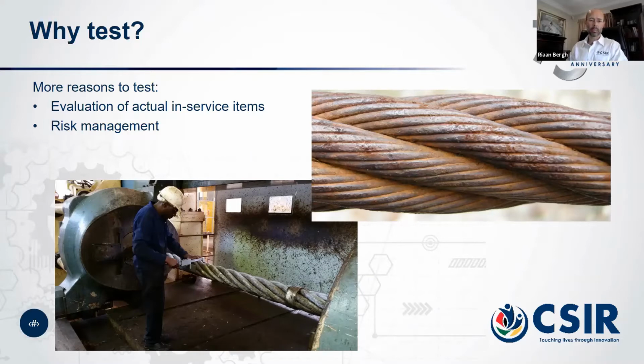But when we tested the rope to destruction, we found that it had only about 38% of its rated strength remaining. And the condition on the interior of the rope was actually quite more severe. Many of the wires were corroded down to needle points, and on the inside of the rope, when we took it apart to inspect it after the test, we found that there were handfuls of corrosion material, rust essentially, that made up the inside of the rope, and not much good steel. And you can imagine that if one hadn't done that test, it could have led to a catastrophic incident if the rope had been put to anything close to its actual intended service strength, maximum service strength.